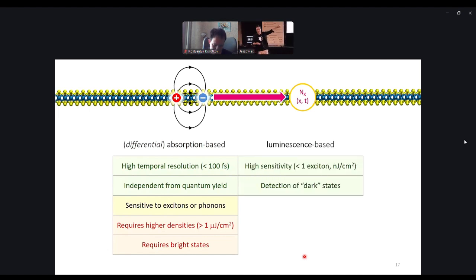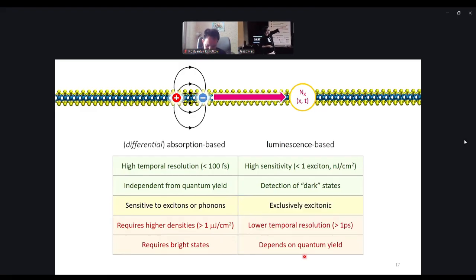One can have quite high sensitivity, so you can perform luminescence experiments time resolved under almost homeopathic conditions of less than 1 exciton per pulse because of the single photon detection capability of modern detectors. Dark states, in a sense, states which do not have strong oscillator strengths, can be detected if they are low-lying states. And the response in many cases is exclusively excitonic or electron-hole pairs. But the disadvantages are, on average, lower time resolution, and typically quite bad because it depends on quantum yield. So if you have a material with a lot of non-radiative channels, it can be tough to measure luminescence.